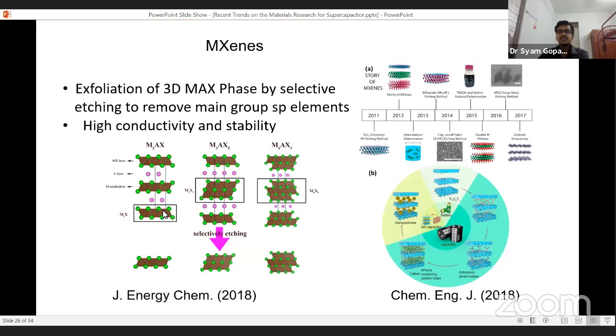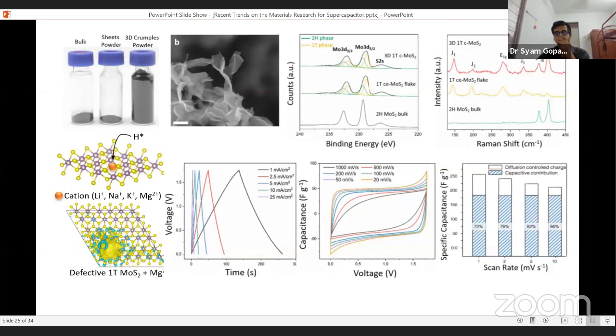Then another research also synthesized this particular molybdenum sulfide for pseudo-capacitor application. And again, this also proved the same. That means the utility of this metallic molybdenum sulfide can give better pseudo-capacitive value compared to manganese oxide electrode. Here the charge discharge is calculated in milliampere per centimeter square, which means the areal capacitance is calculated. So it's giving a very good areal capacitance compared to the manganese oxide. So this metallic molybdenum sulfide can also be a future exploration area for pseudo-capacitor research.